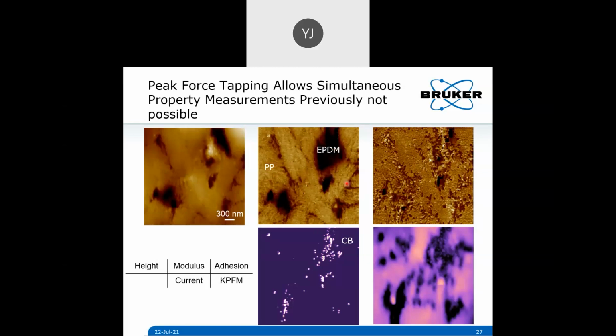And once you look at, let's say, the work function or the current data, you can identify where the carbon black is, right? The carbon black is the most conducting material. The polymers aren't. And you can clearly identify that they are much, much smaller. So even though the modulus data is not so clear, you can clearly identify them once you do the electrical measurements. So you are able to do all this through PeakForce tapping.